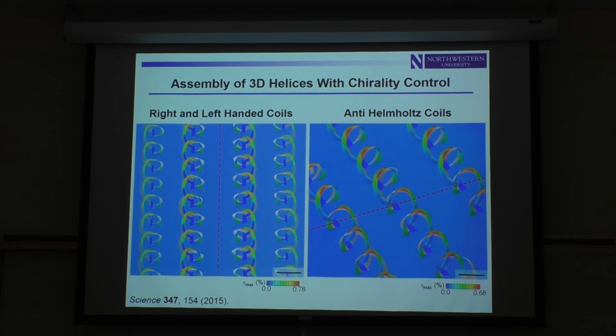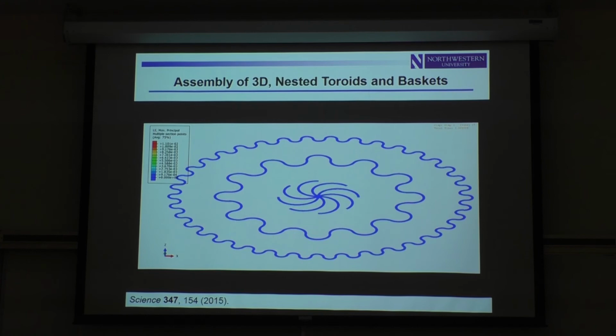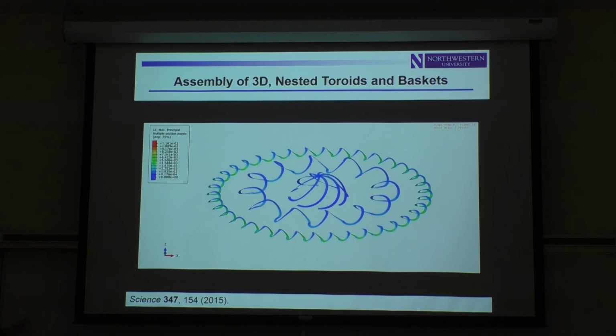So you can do all kinds of different coils. You can control the handedness of the coils by controlling the geometry of the precursor. We can do right and left-handed coils. We can do anti-Helmholtz coils, so right to left with an abrupt shift in the handedness at a predefined location. We can also do toroids, so instead of just uniaxial stretch, you can do biaxial stretch and then close these filamentary structures on themselves. So this will generate one toroid, another toroid, and then sort of a funny basket structure in the middle upon release of pre-strain, and you see that happen spontaneously. Again, relaxing pre-strain, geometric transformation, planar to 3D, in that kind of way.